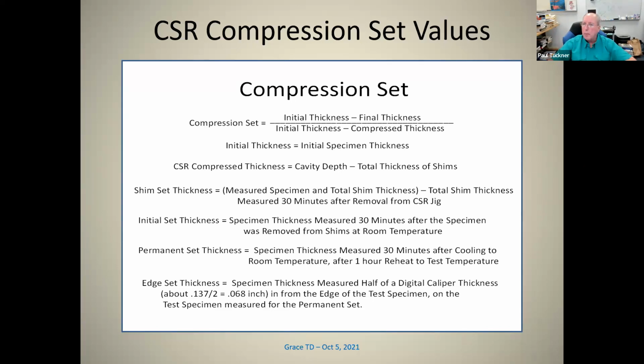And that's what I call the permanent set, which is a standard compression set kind of test. And then what you do is you take a digital caliper and you measure the thickness at the edge of the specimen. And that's what I call the edge set.